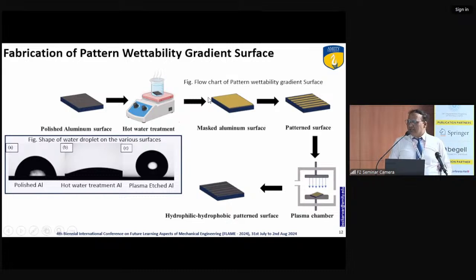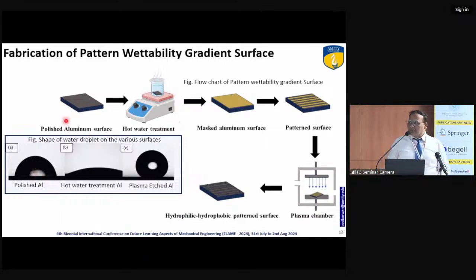So what happens by the hot water treatment? Where the tape was, these are hydrophilic, and when there is plasma etching, the rest becomes hydrophobic. You can see this is the polished aluminum smooth surface. The contact angle is close to 60 degrees. After the hot water treatment, the contact angle is 20 degrees, and after the plasma etching the contact angle is around 140 degrees.